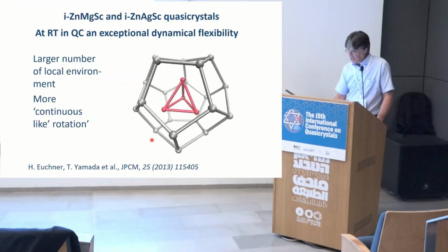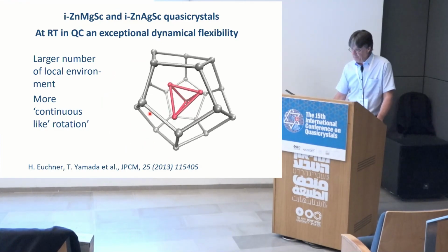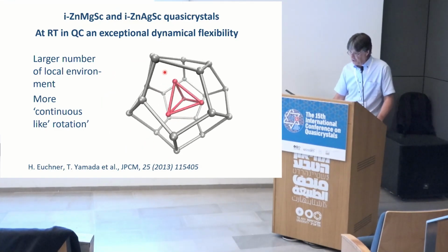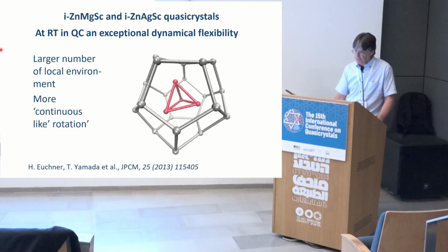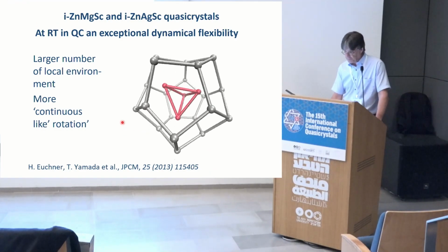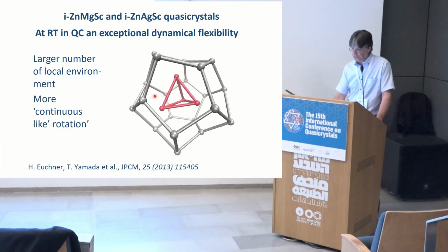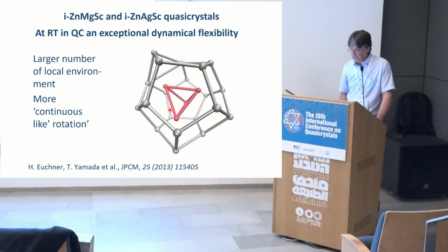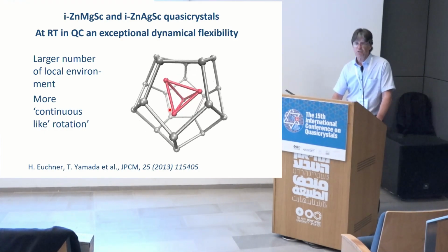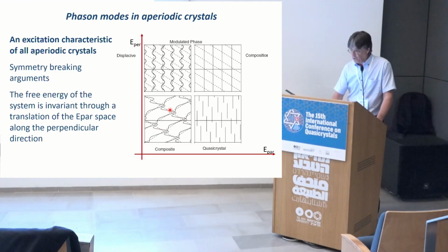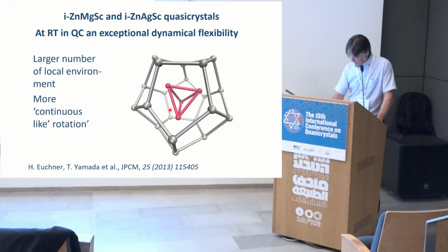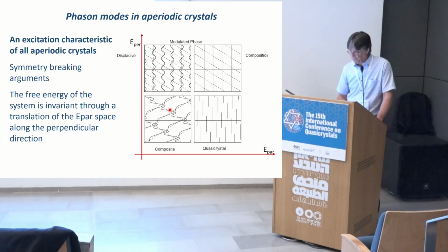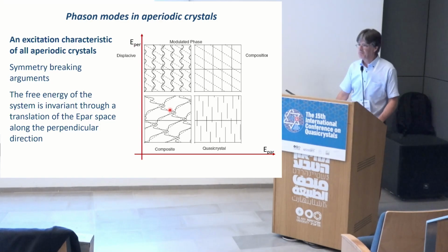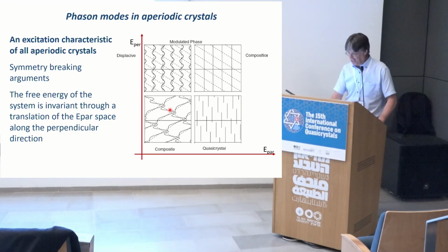And the same is going on in the zinc-scandium quasicrystal, or zinc-magnesium-scandium quasicrystal. You have a kind of continuous rotation, but again, you have this central tetrahedron that plays an important role, and which maybe we can relate to phason modes. Oh, sorry, I may be a little bit long. I have maybe 5 minutes, and I'll take the last 5 minutes to say a few words about phasons.